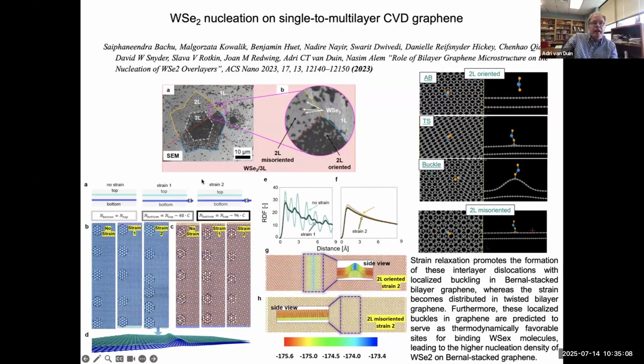This was indeed confirmed experimentally, where we see that the misoriented graphitic areas lead to very strong chalcogenide deposition, while the oriented areas have no tungsten diselenide deposition at all. Our simulations managed to explain this and also give clues to the experimentalists on how to use this concept. This was published in 2023.